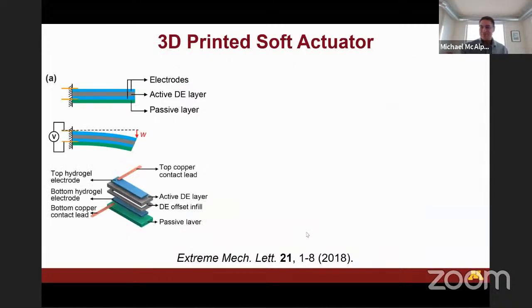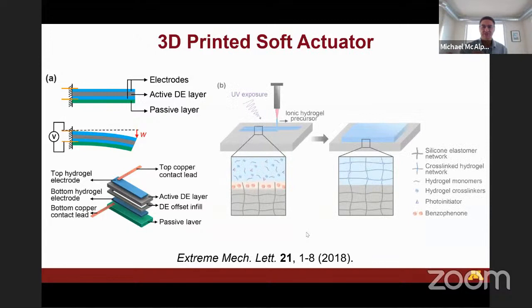And as a separate paper, this was published in EML. Actually, we wanted to demonstrate that we could also 3D print an electrically driven actuator. The difference here is we added this passive layer, so that instead of it flattening like Ziguang showed, it will actually bend. And the way we were able to do this was we incorporated barium titanate particles in the silicone as a composite. And so the entire structure was fully 3D printed.